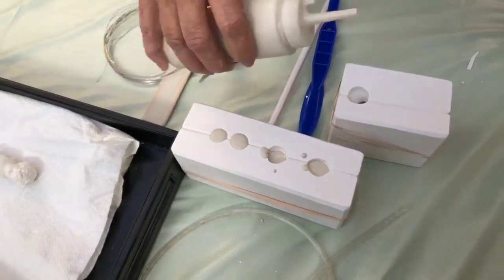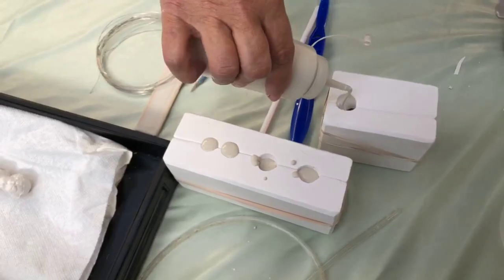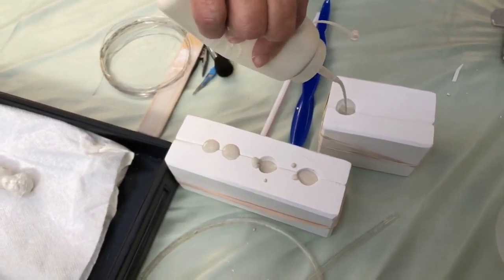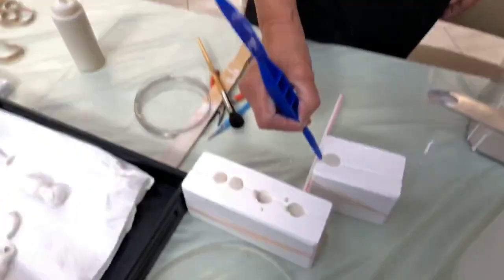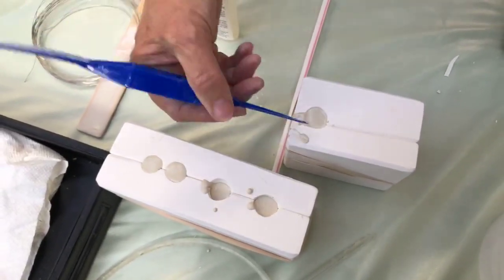And this is a bigger one, so I could probably pour it directly from this, but with All-Bisque dolls, I really like to use a little squirt bottle. You have to keep a consistent pouring, because if you stop, the clay has a memory and it will make lines. So you want to make sure it's beautiful bisque. So you pour it and let it sit for a few minutes, because what it's doing is building up a wall. You see how quickly it becomes clay. It sets, yeah, it really does.